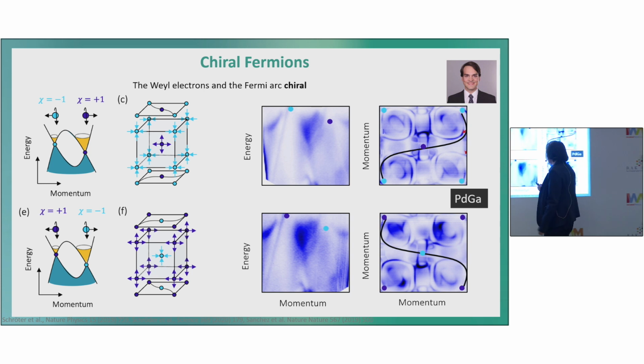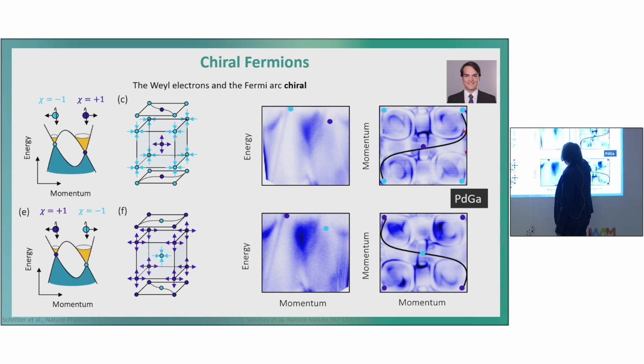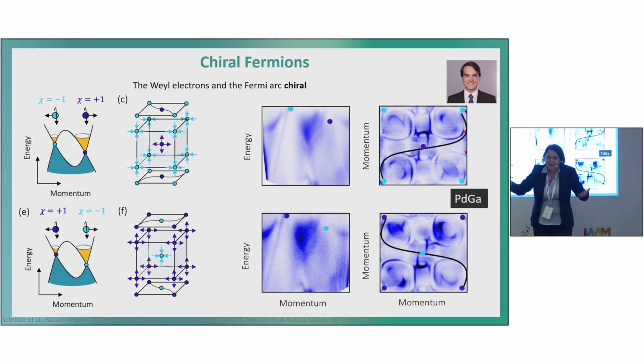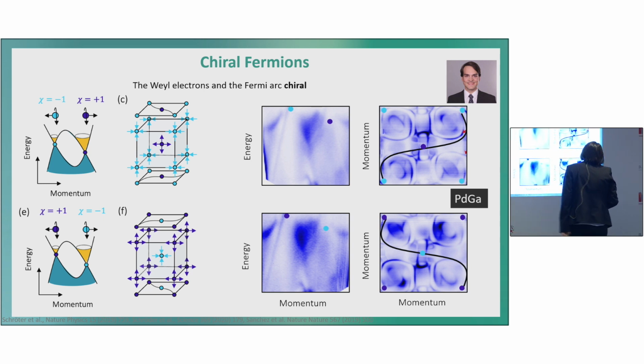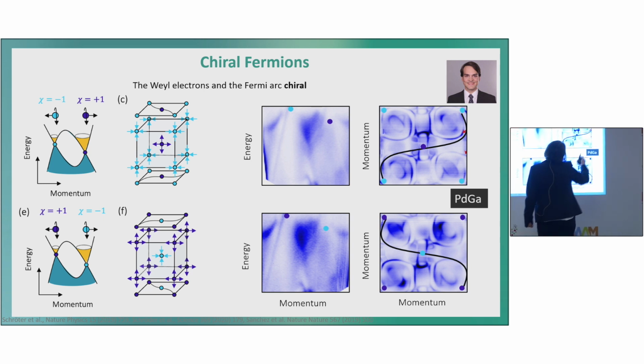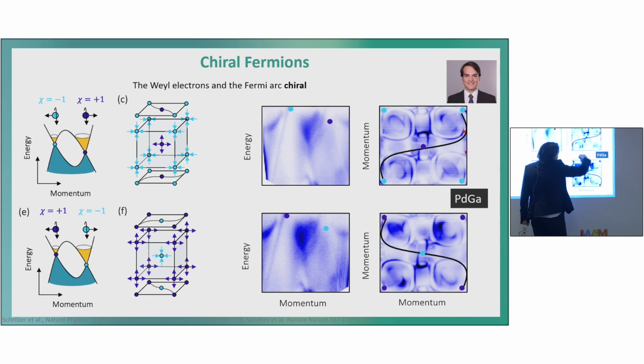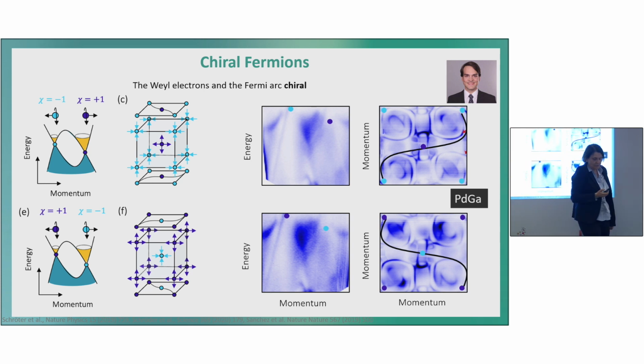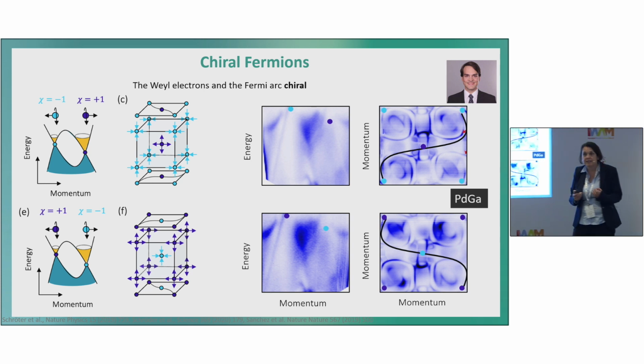If we do angle-resolved photoemission, this is a band structure, we cannot see the color of the Weyl points, we only see the Weyl points. But if we look at the surface state, we see that the surface states are chiral for the different enantiomers. So we have different chirality of the surface state for the two enantiomers.